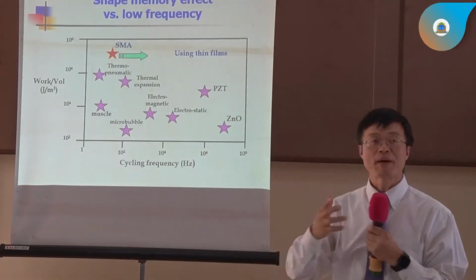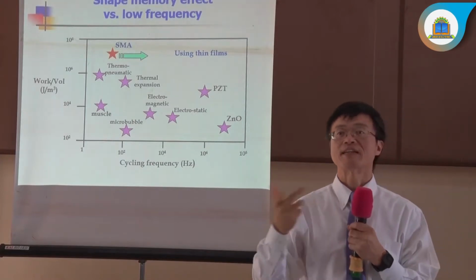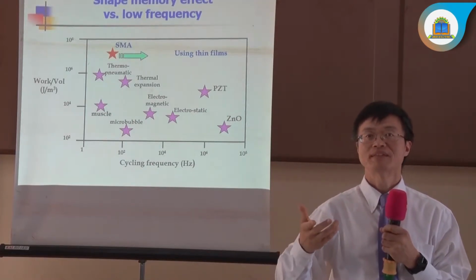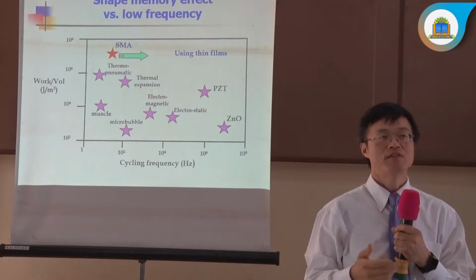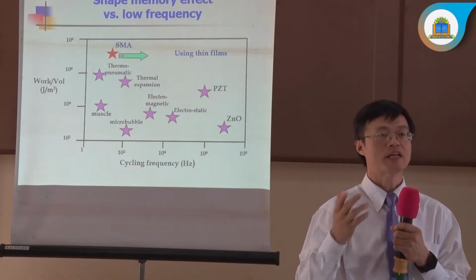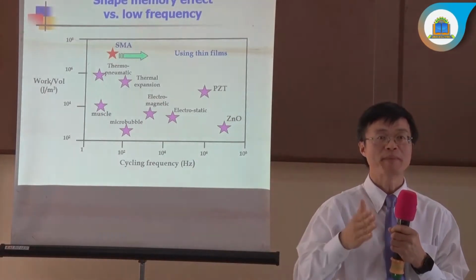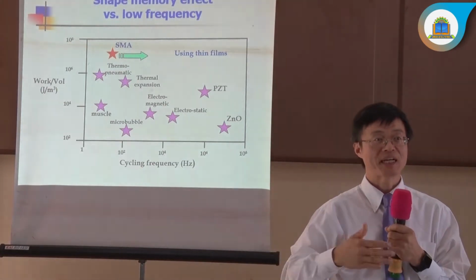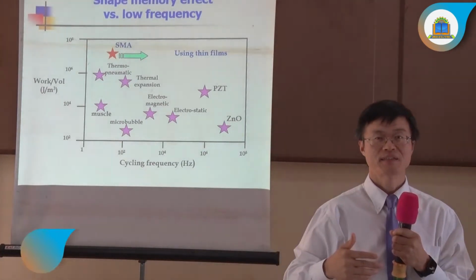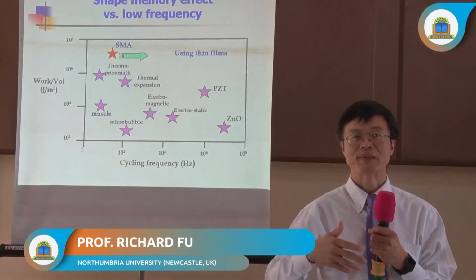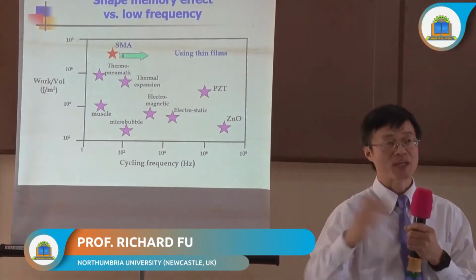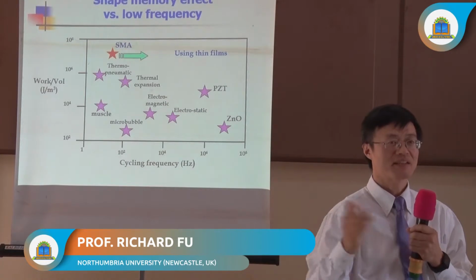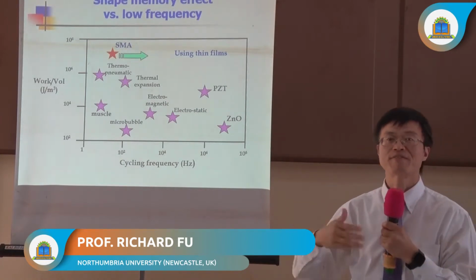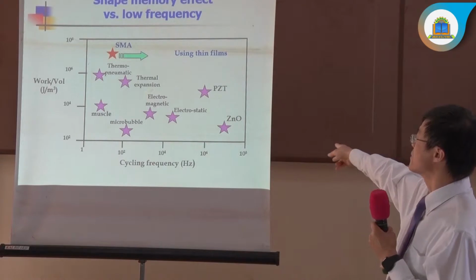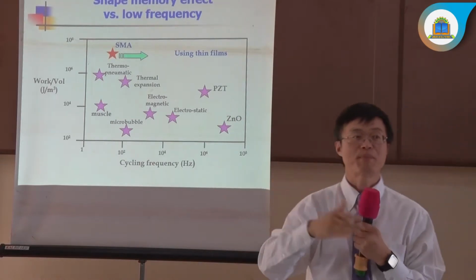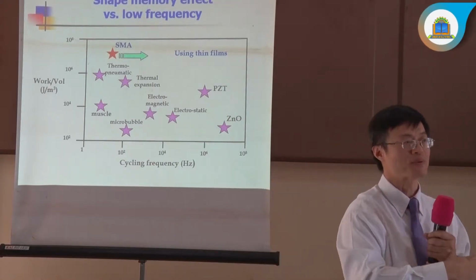But the trouble for shape memory is because it's using heat. We heat up the material to change shape. For all the principles using the heating method, the problem is the frequency. You can heat it up very fast, right? But cooling down is much more difficult. So that means you cannot operate very fast. So for some application, we need it very fast. For example, piezoelectric is much better in high frequency. Shape memory or thermal, very low frequency.